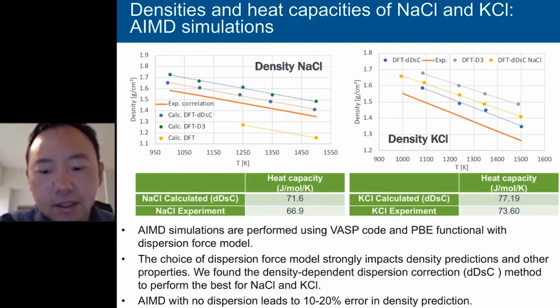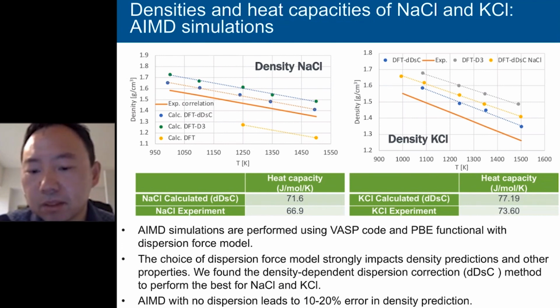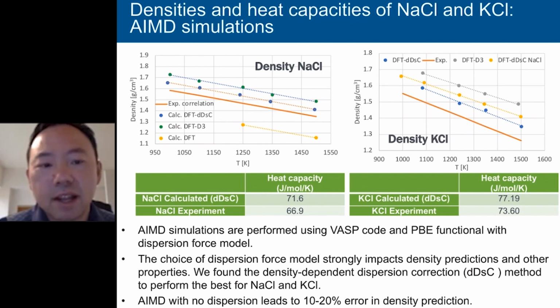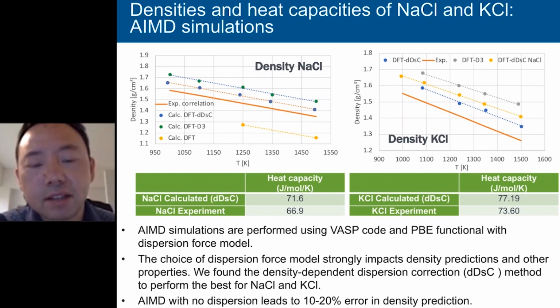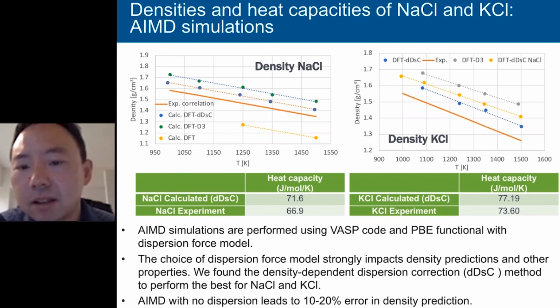So the key conclusion is that Ab-Initio MD has to be performed together with a suitable dispersion force model. David found that the most accurate one is the so-called density-dependent dispersion correction model, the DDSC model. If you look at the figures on the left, the blue circles are from DDSC calculations. They give excellent agreement with experiments. The same conclusion also holds for potassium chloride.